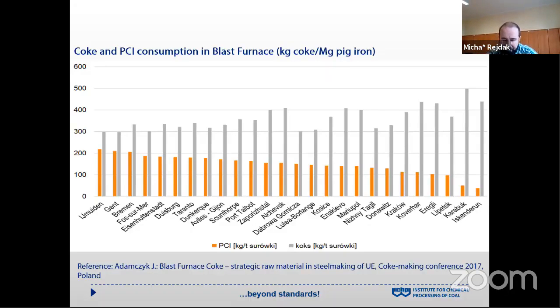For example, in this slide, we can see the consumption of coke and PCI, I mean pulverized coal injection, per ton of pig iron. The higher the PCI usage, as we can see, the lower the coke consumption. As shown in the diagram, the coke consumption is over 300 kilograms per 1 ton of pig iron produced.